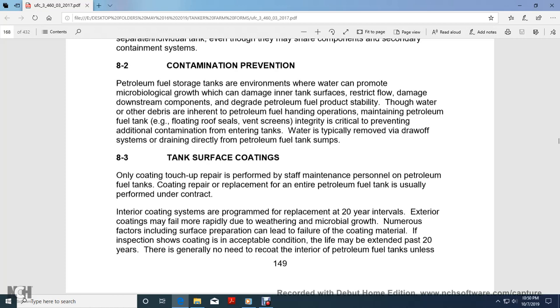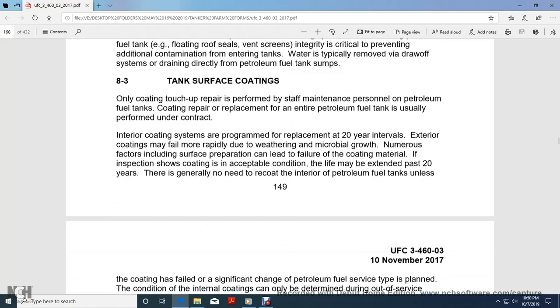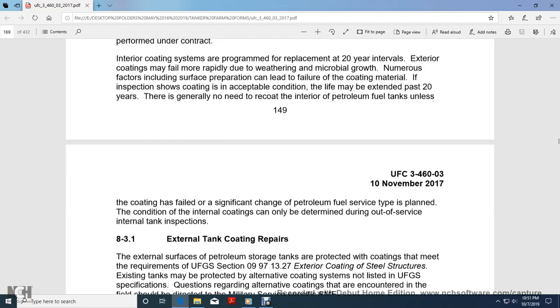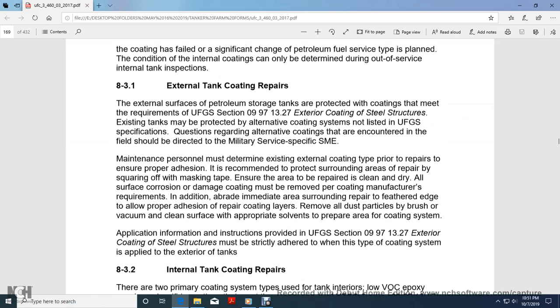Only the coating touch-up repair is performed by the staff maintenance personnel with the petroleum fuel tanks. Coating repair with the replacement of the entire petroleum fuel tank is usually performed under contract. Interior coating system programs call for replacement at 20-year intervals. Exterior coatings may fail rapidly due to weathering and microbiological growth. Numerous factors, including surface preparation, can lead to failure of the coating material. If the inspection shows the coating is in acceptable condition, life may be extended beyond 20 years. There's generally no need to recoat the interior of petroleum tanks unless the coating has failed. or a significant change of petroleum fuel service type is planned. The condition of the internal coatings, can only be determined during the out-of-service internal tank inspections.